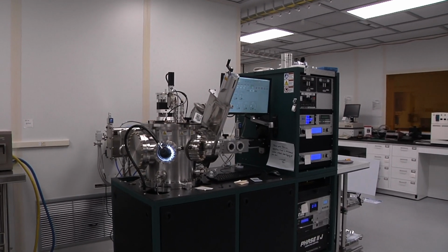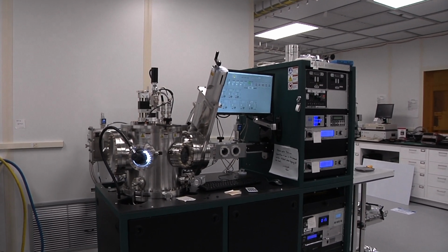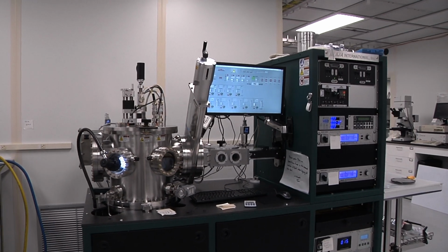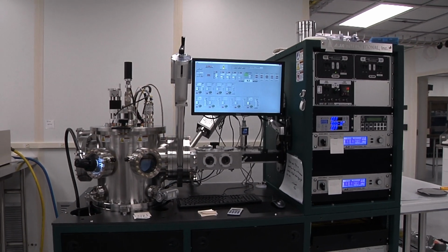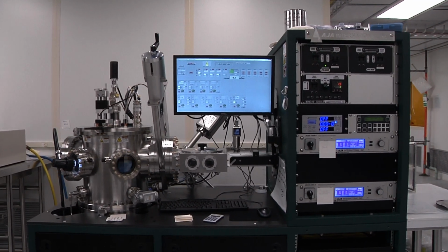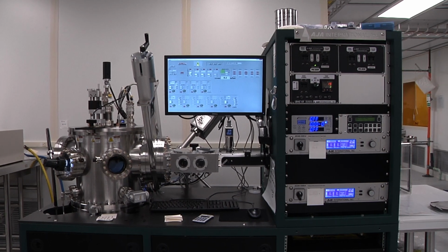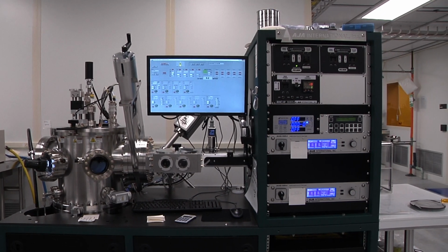So I had a very good PhD student, Nate Rogers, who worked on this. We used an AJA deposition system that's at the Cornell Nanofabrication Facility. You're looking at a picture of that one here. That's what that machine looks like. And we used that to work out the parameters. And what we did was we figured out a set of parameters that we could use during sputter deposition to make thick films that were fairly stress-free.